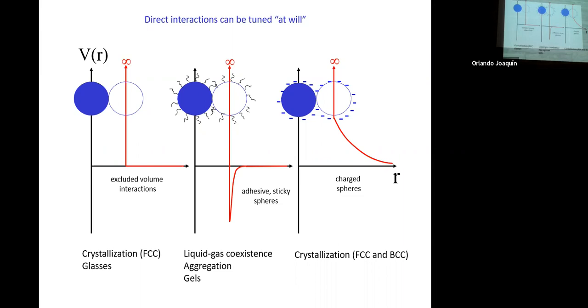You can also coat particles, for example with polymers on the surface. If you dissolve these particles in a solvent that is a poor solvent for the polymer, these brushes want to dissolve into each other - they want to overlap rather than being in the solvent. Then you get an attractive force, which is very short range, about the size of the polymer, and you get what people call an adhesive or depletion-like layer.